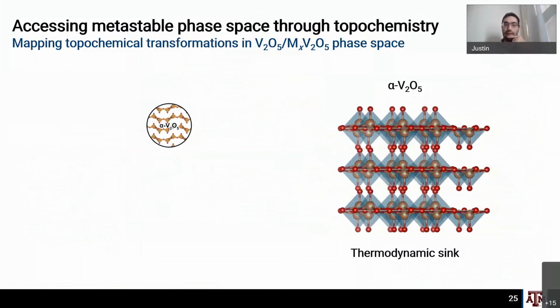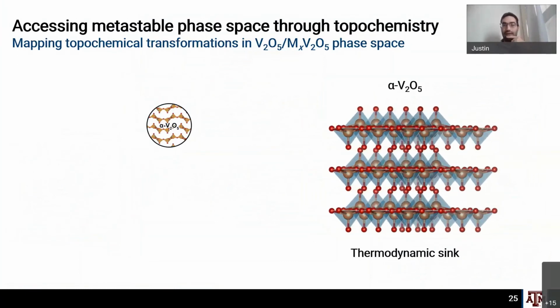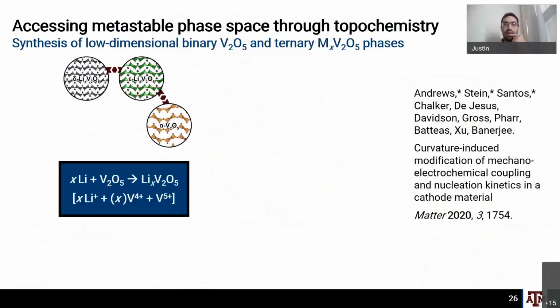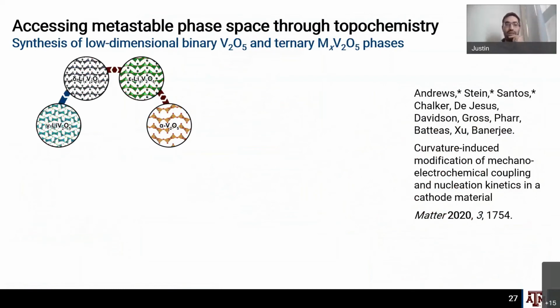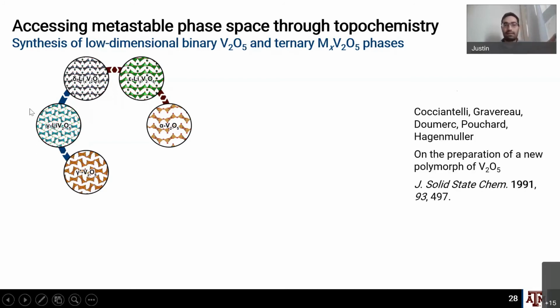So I mentioned before, this is the structure of V2O5. This is the up, down, down VO5 square pyramid structure of V2O5. And as I showed before, we can intercalate lithium, and what that does is pucker the layers and give us different ternary phases. But we hit this at about x = 1, we get lithium V2O5, this gamma phase that has an irreversible phase transformation where we depart this up, down, down structure and go into an up, down structure. So this is a fundamentally different V2O5 sublattice. But what's really interesting is that I said it's irreversible. And so when we pull the lithium out, we actually stabilize a metastable polymorph of V2O5, with different connectivity but the same composition.